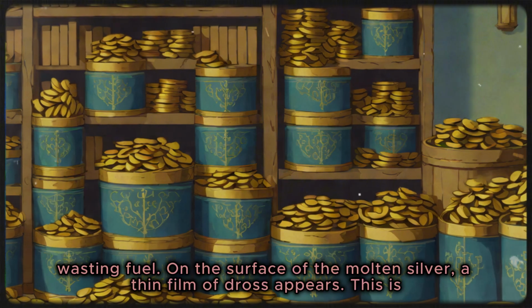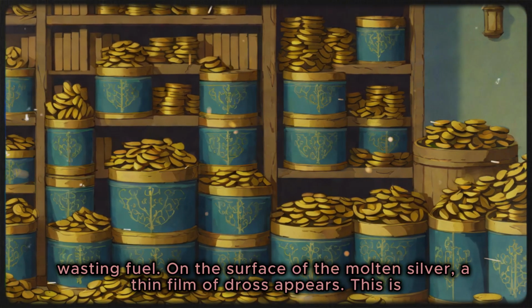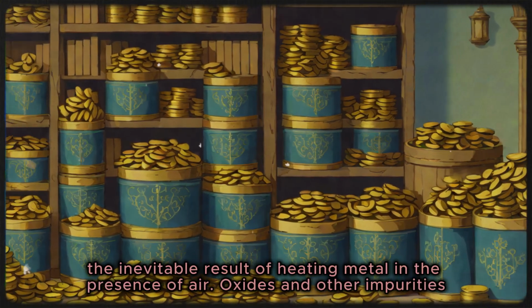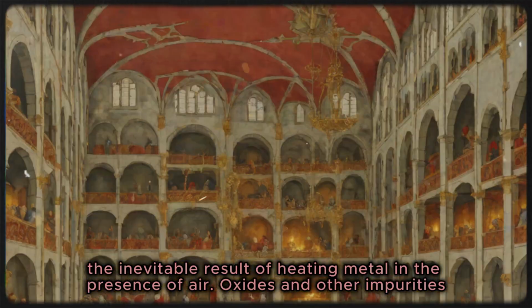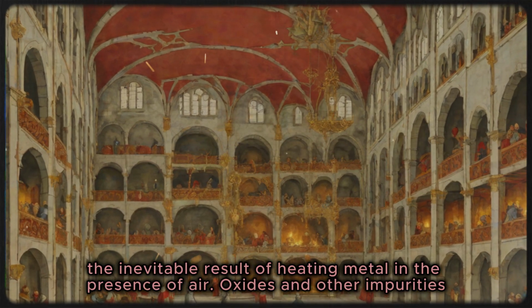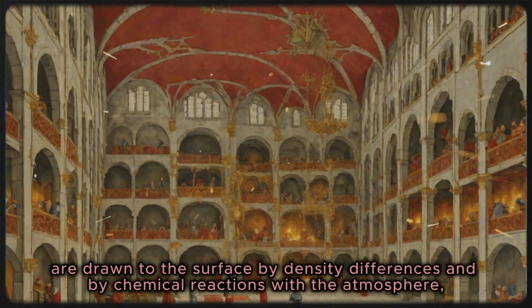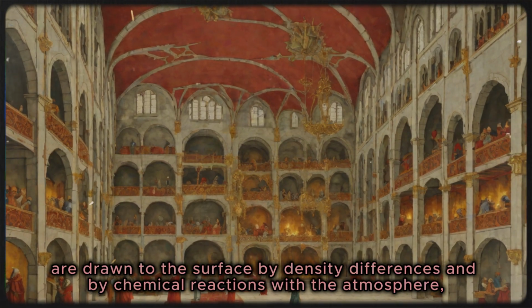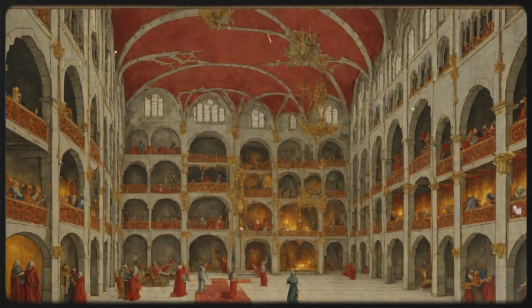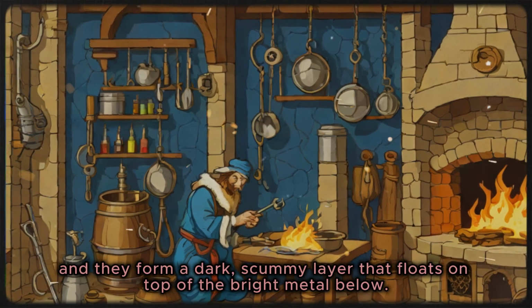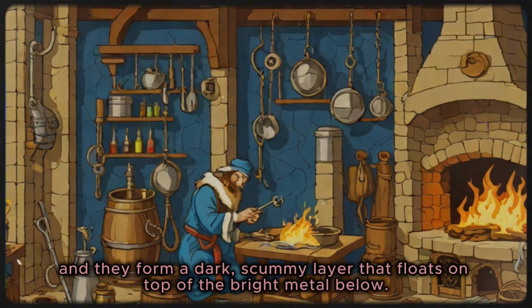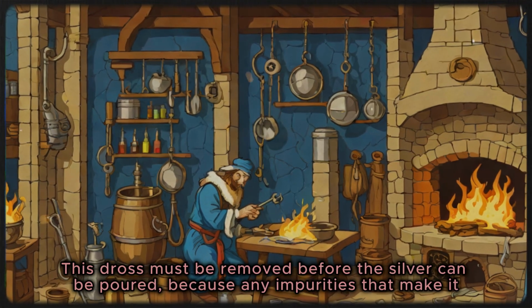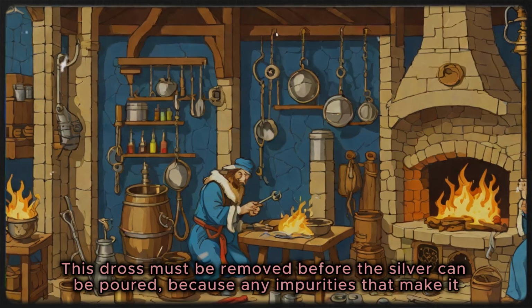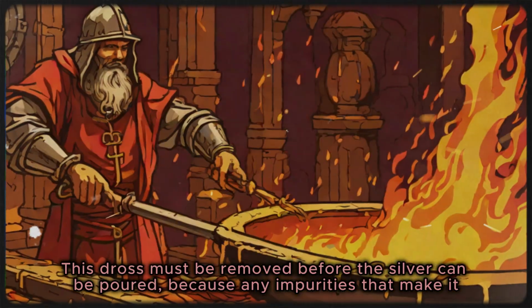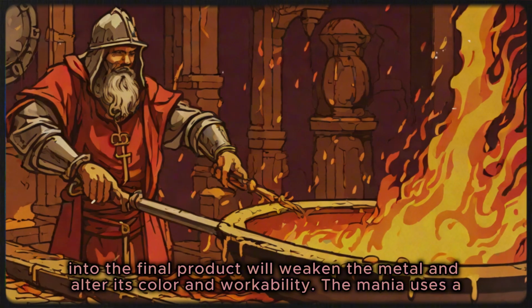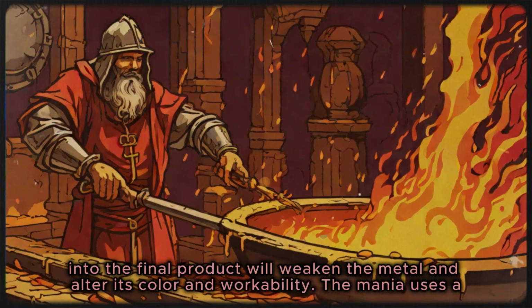On the surface of the molten silver, a thin film of dross appears. This is the inevitable result of heating metal in the presence of air. Oxides and other impurities are drawn to the surface by density differences and by chemical reactions with the atmosphere, and they form a dark, scummy layer that floats on top of the bright metal below. This dross must be removed before the silver can be poured, because any impurities that make it into the final product will weaken the metal and alter its color and workability.